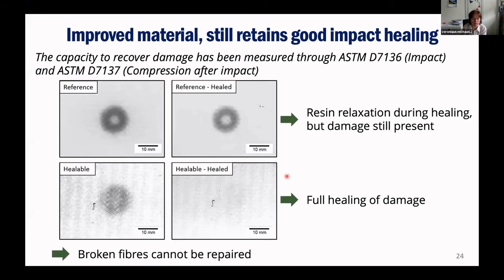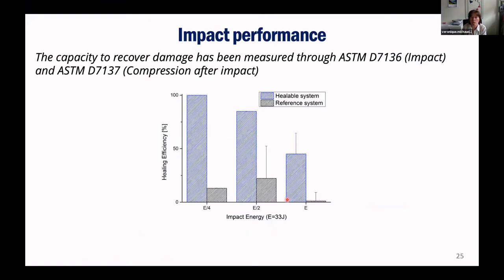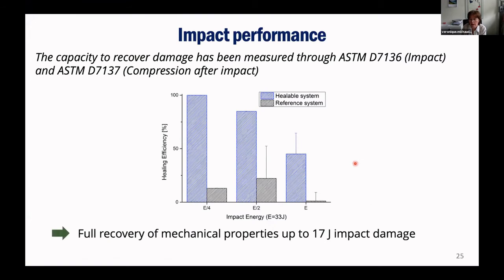And if you compare the healable system after impact, the reference is not really healed. Of course, the broken fibers still cannot be repaired, but we see also that the resin, if the reference is pure epoxy, has some relaxation also if you heat it up, but with damage, whereas with our system, we have the full healing. And then we also looked at the impact performance. The reference system after healing, 150 degrees again or something for a few minutes, was healing a bit, but our system gave decent healing efficiency, and after up to 17 joules impact damage, which is okay.